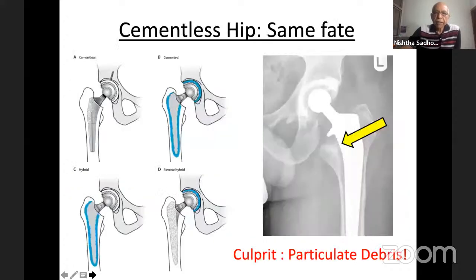So with that, the cementless hip evolved, hoping that it would bypass the so-called cement problems. However, whatever permutation combination was used, whether it's completely cementless, or hybrid in which the stem was cemented or the cup was cemented and the rest was uncemented, the problem still remained the same, i.e. the stem and the cup got loose. So eventually the culprit was determined as the particulate debris.